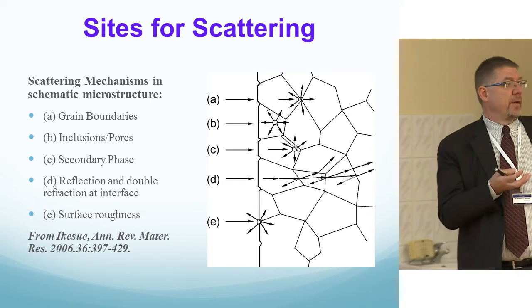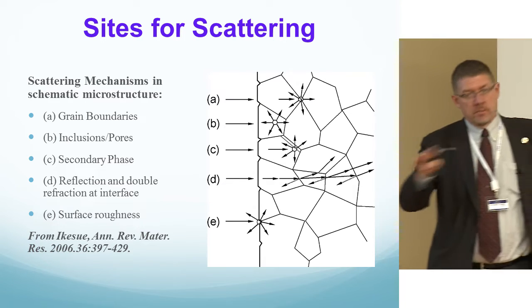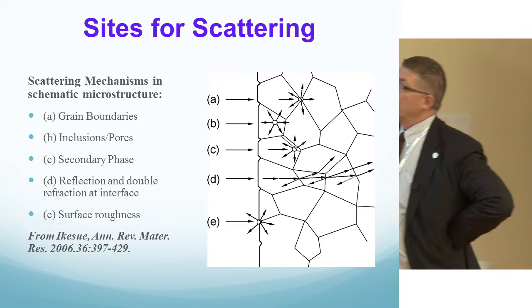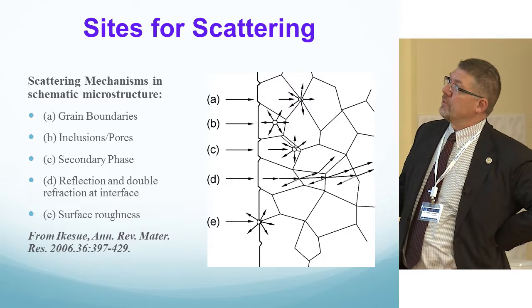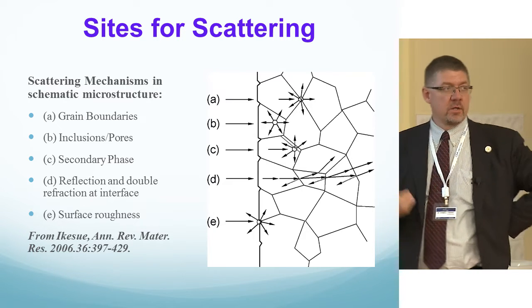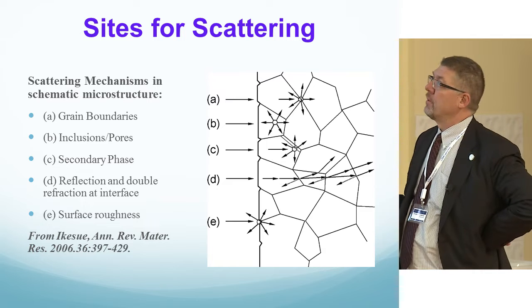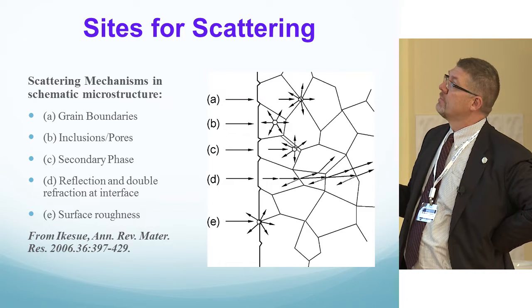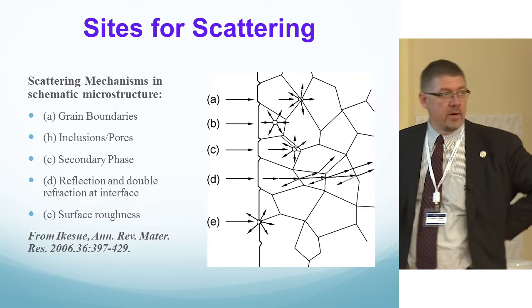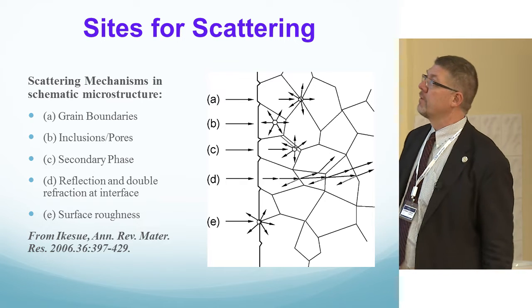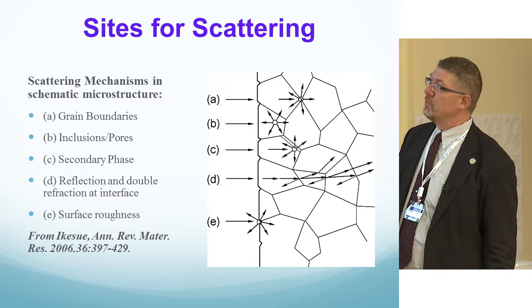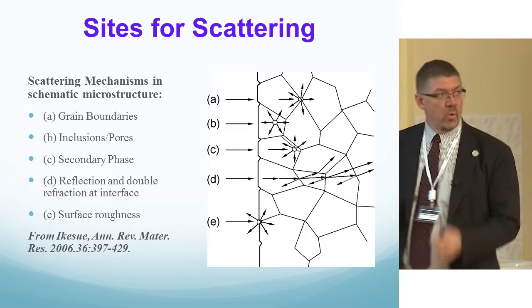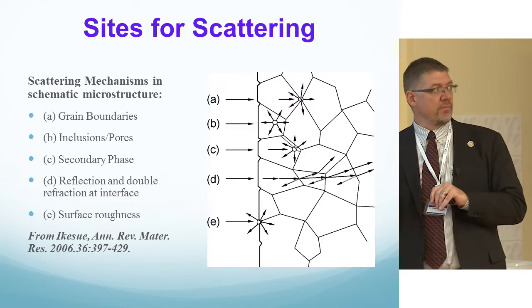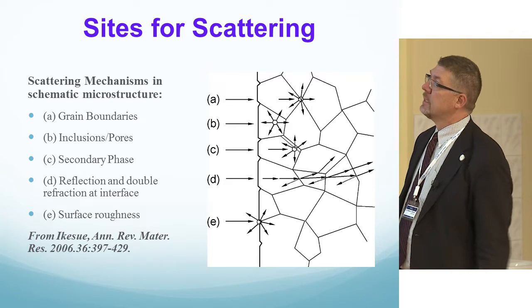As I mentioned, scattering is a problem. So birefringence throws that out. There are other scattering areas, as you can see here. Some of the mechanisms that cause scattering in a polycrystalline material are grain boundaries. If you have a grain boundary here that's not aligned or is a bad grain boundary, that can scatter your incoming photons. Then inclusions or pores that get trapped within the grain. I'll show you photographs of all of these in a moment.